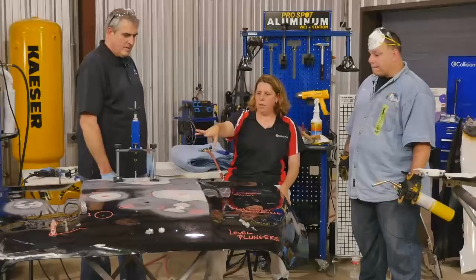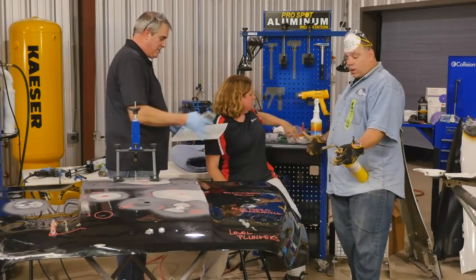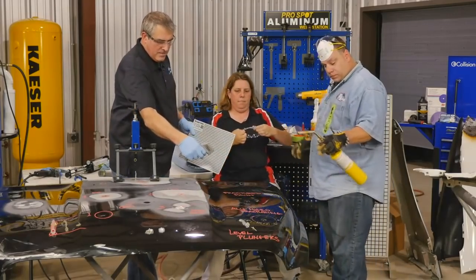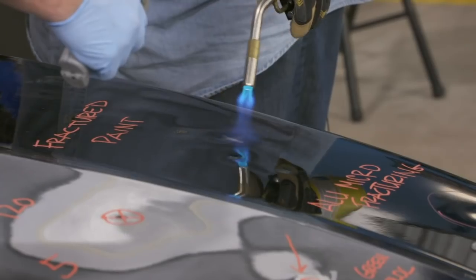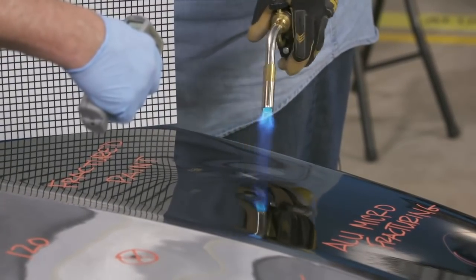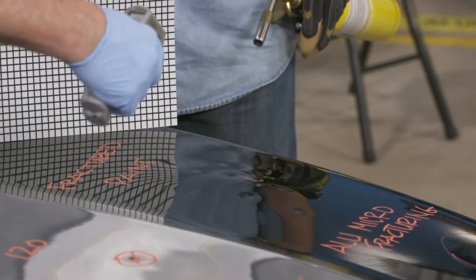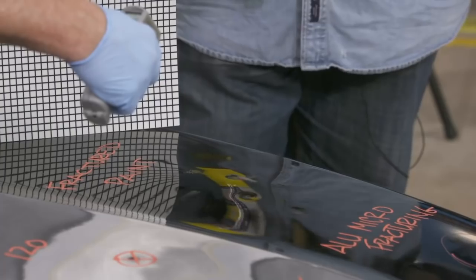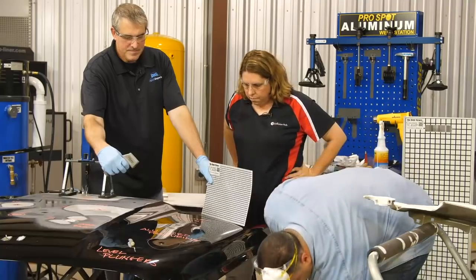So why don't you take us through the steps, Larry and Mark. We're going to do it right now — we're going to heat this up. Watch how fast this dent moves. Okay, now looking at this, we're at 92°F — so now you know how hot it is in the studio. Now we're at about 350°F, and it's gone. See how far up it came? It rises. Now you'll be shocked at how it'll flatten out. You can let this naturally cool, which is probably going to take about 10 to 15 minutes. We're at 275°F right now. You can see we've got no evidence of that original dent. Go out a little to the right — what's your temperature out there? 195. So that's a lot of heat travel. I'm at 137 still — too hot to really touch.